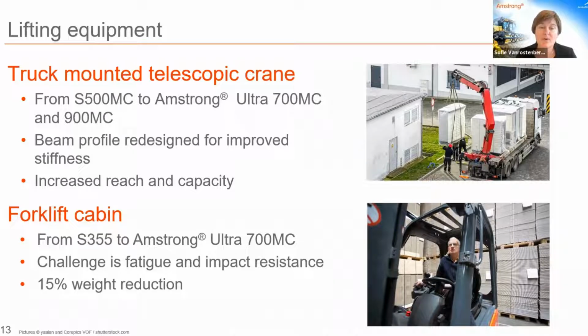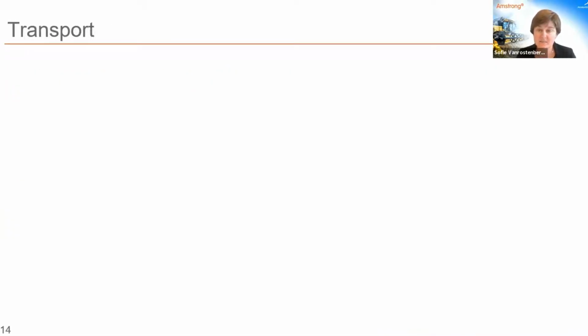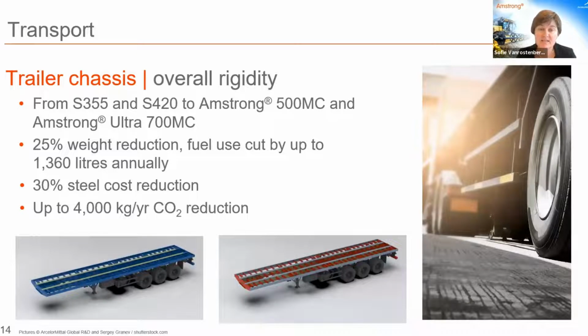A last group of applications we would like to highlight is the transport sector, and more specifically zooming in on a trailer chassis case. We developed a steel solution replacing the S355-420 grade by an Armstrong 500 and 700 MC. This case study has shown that the weight of a typical existing chassis can be reduced by about a quarter without affecting the performance. The projected mass saving reduces fuel use and can save up to 4,000 kilograms of CO2 emission per year per trailer produced. So this will, of course, have a major impact on helping to achieve the goals of the European Green Deal, for instance.